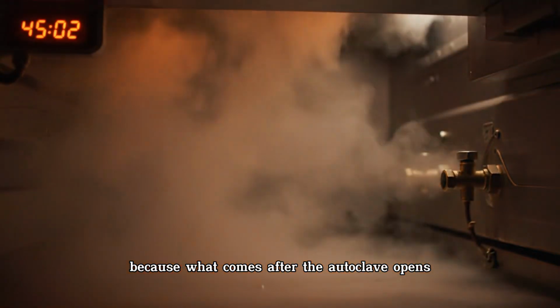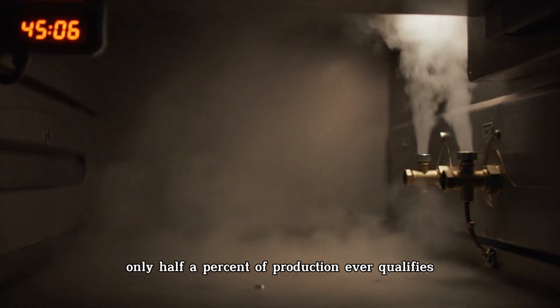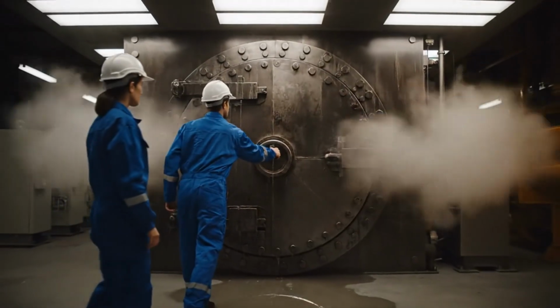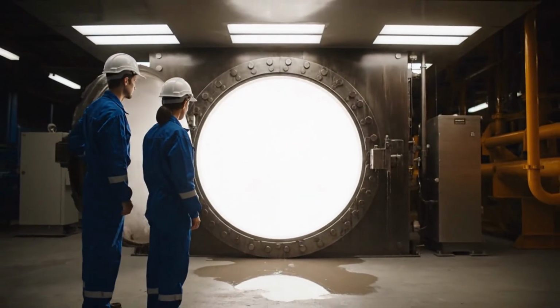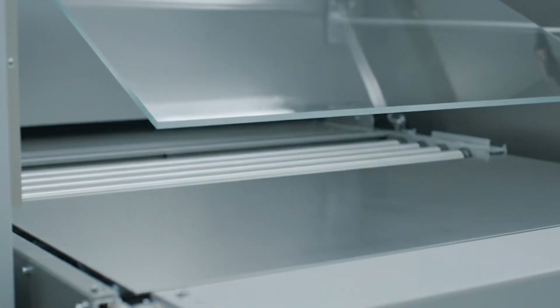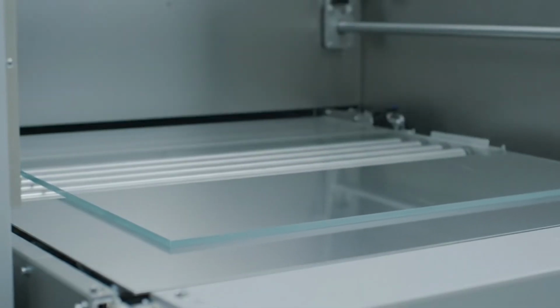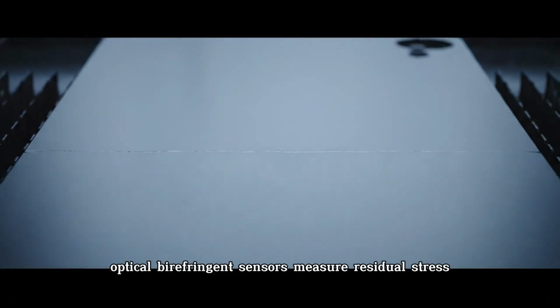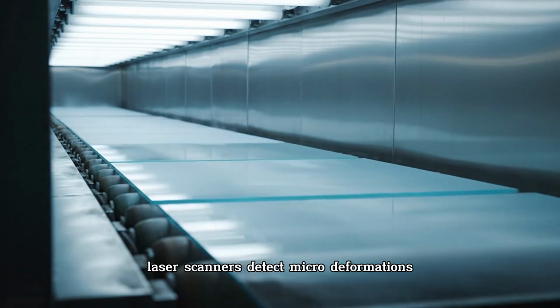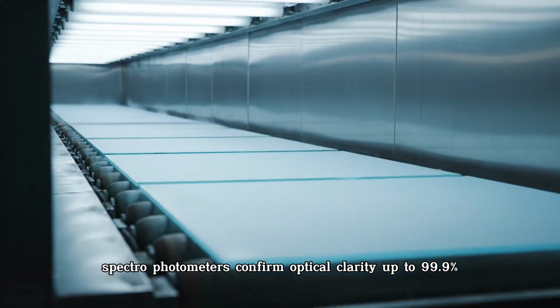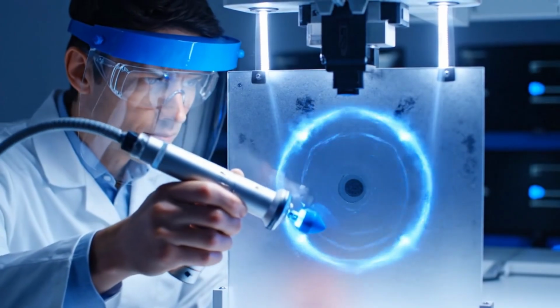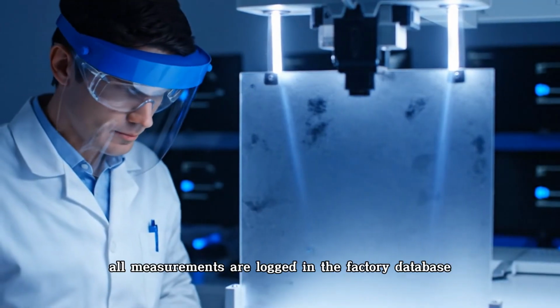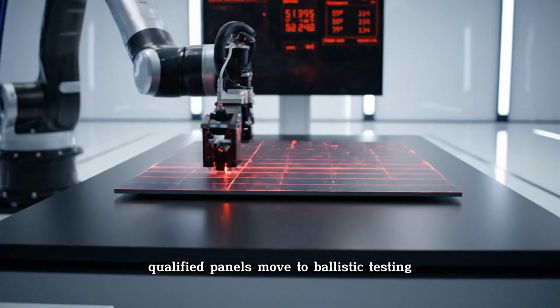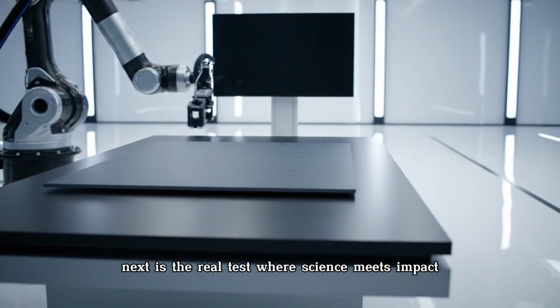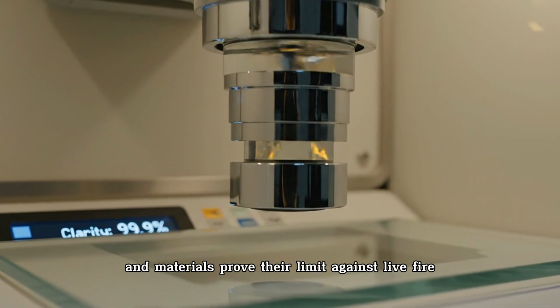Stay, because what comes after the autoclave opens explains why only 0.5% of production ever qualifies for final approval. The chamber cools. Laminar air flows across the surface to cool it evenly. Optical birefringent sensors measure residual stress inside the glass. Laser scanners detect micro-deformations and surface curvature. Spectrophotometers confirm optical clarity up to 99.9%. Rejected panels are marked and sent for recycling. All measurements are logged in the factory database. Qualified panels move to ballistic testing. Next is the real test, where science meets impact velocity and materials prove their limit against live fire.